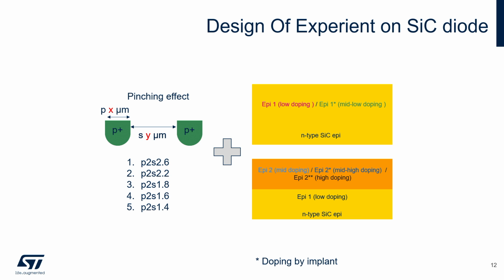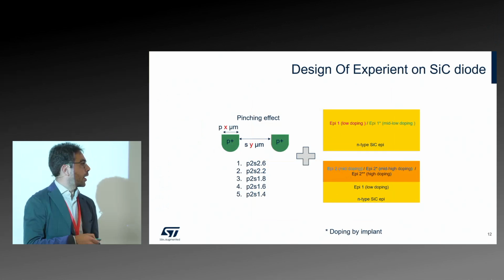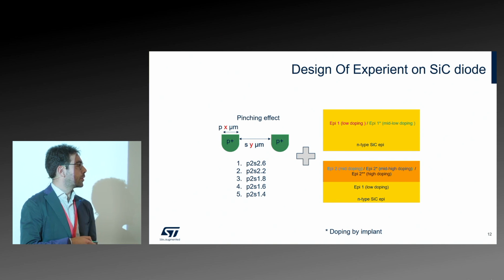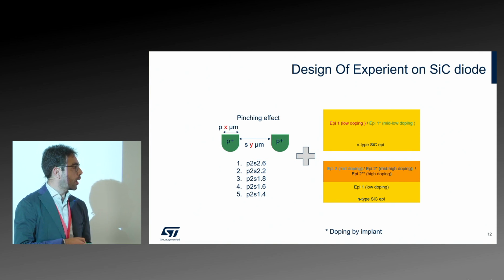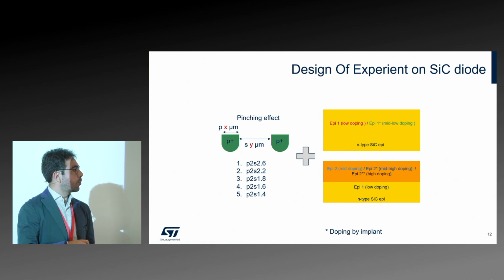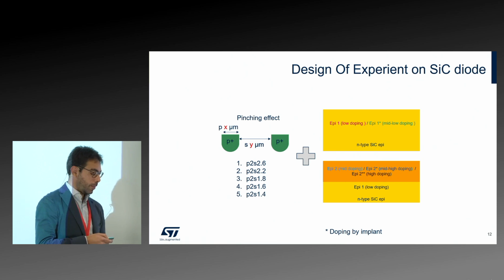So I sketch here epi 1, which we can consider a low doping epi. Epi 1 star, in which I dope this epi by implantation, so it shows higher doping than epi 1. And then I also combine the different pitch with an epi 2 that has higher doping than epi 1, that is grown on epi 1. And again, I implant epi 2, I double implant epi 2, and see what happens.